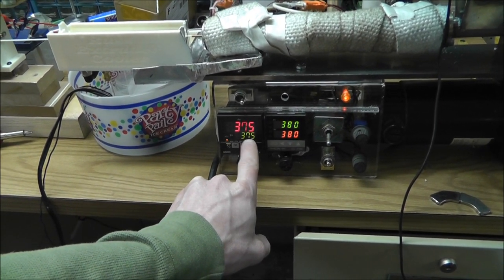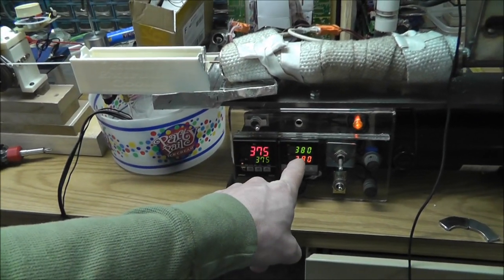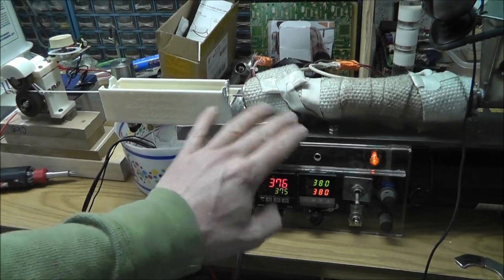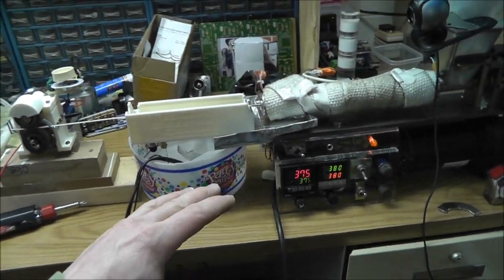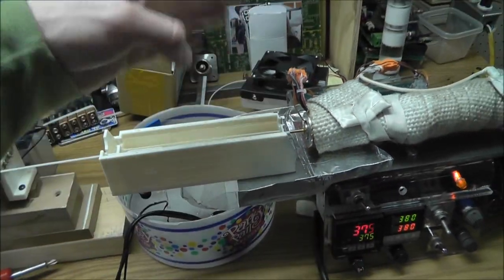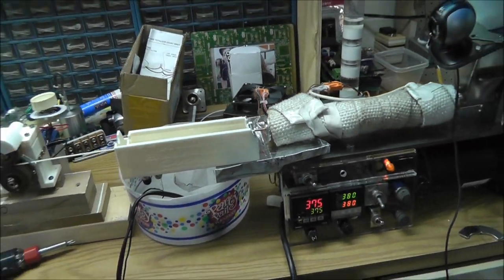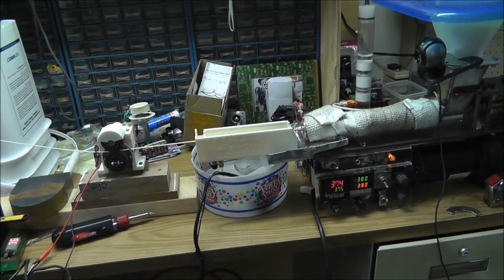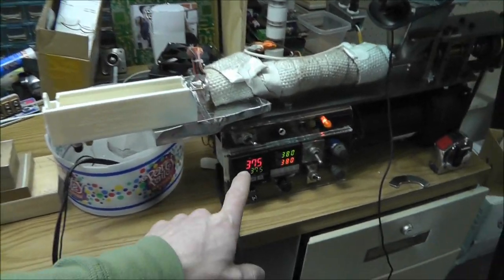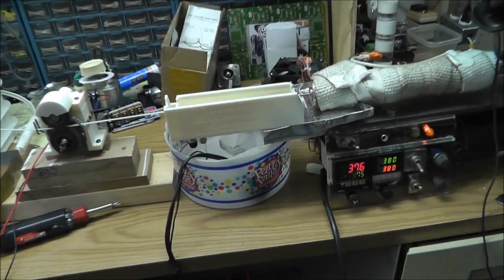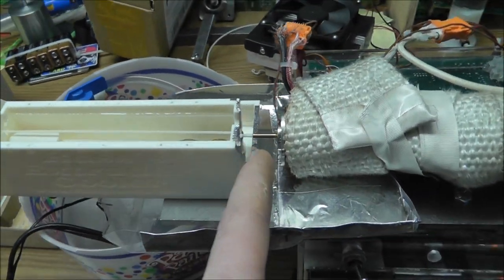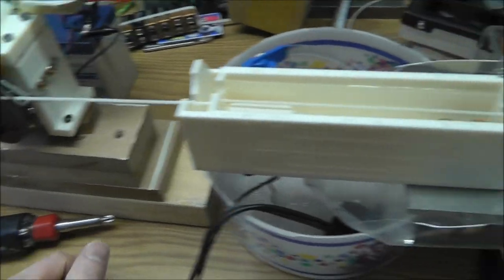And what I did is I lowered the temperature of the nozzle here and this a little bit higher. So it's kind of the opposite of what you would normally do in an extrusion process. But the thing is if I get this too hot, this starts getting real squirrely. And you saw that in my time lapse of my last one that I made. I figured out the temperature is too high. The reason is it's squirting out and it's kind of just doing whatever it wants. Where here it's actually being pushed out and I'm pulling it to the right diameter.